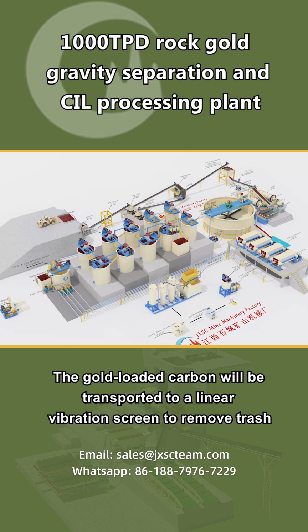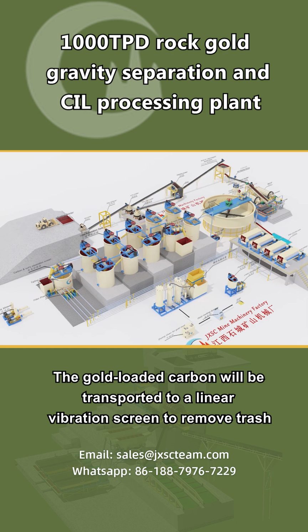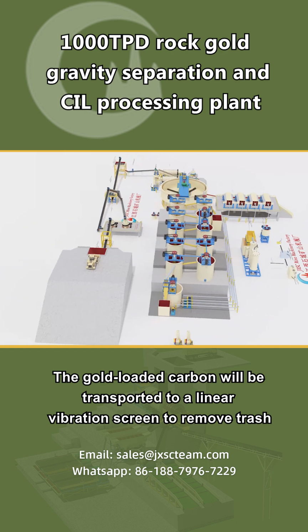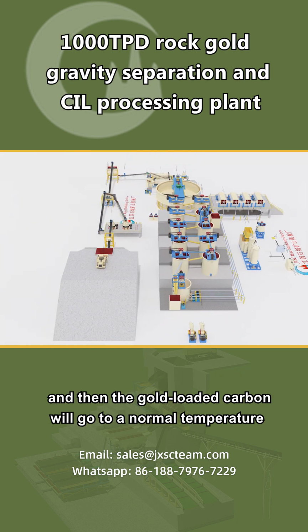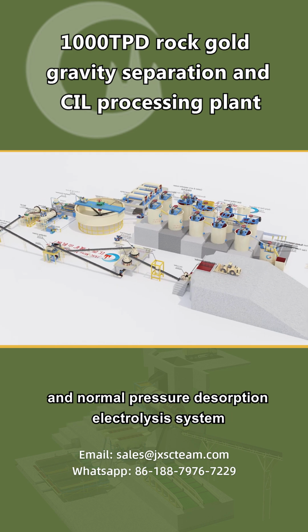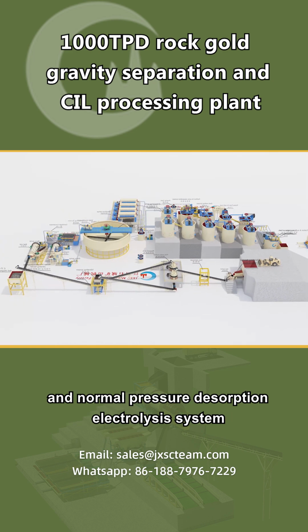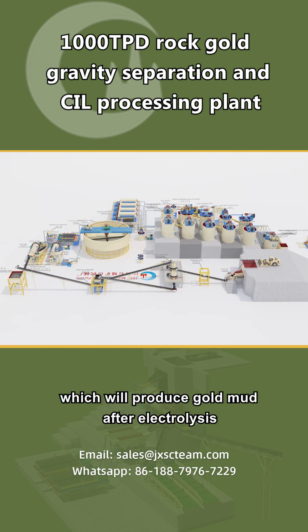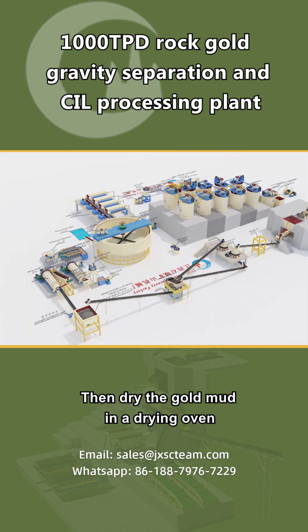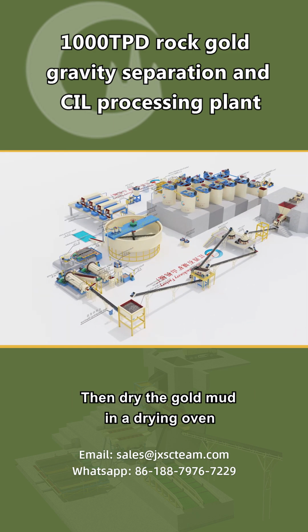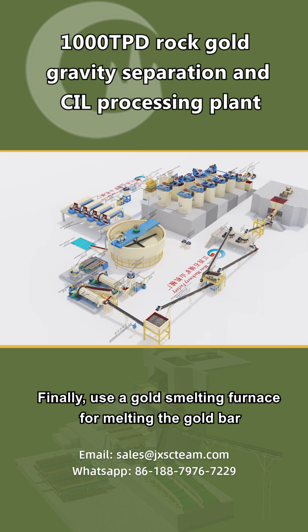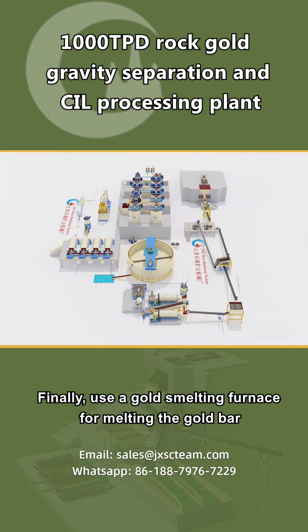5. Gold-loaded carbon desorption and electrolytic system. The gold-loaded carbon will be transported to a linear vibration screen to remove trash, and then the gold-loaded carbon will go to a normal temperature and normal pressure desorption electrolysis system, which will produce gold mud after electrolysis. Then dry the gold mud in a drying oven. Finally, use a gold smelting furnace for melting the gold bar.